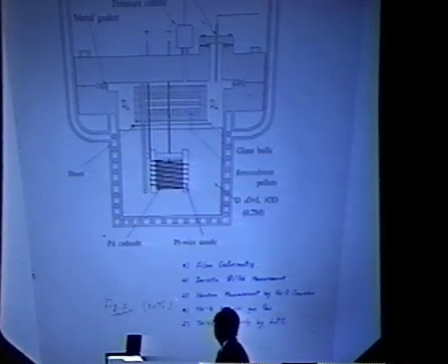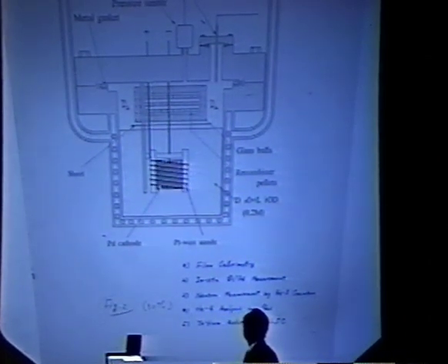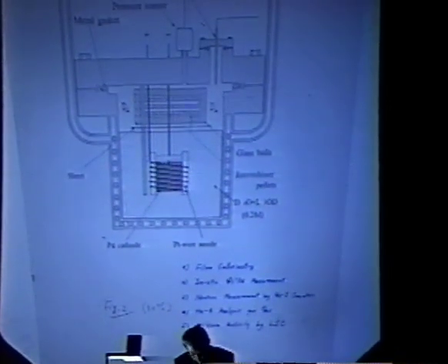So this is a closed cell. We are doing flow calorimetry to detect the excess heat coming out from the cell, and also measuring in situ the D/Pd ratio from the pressure change of the upper room of the cell. And also monitoring the neutron by a helium-3 counter outside. We are also analyzing the gas in this upper room of the cell before and after the electrolysis run using a quadrupole mass spectrometer. And we are also making a tritium activity analysis based on the liquid scintillation counting technique.